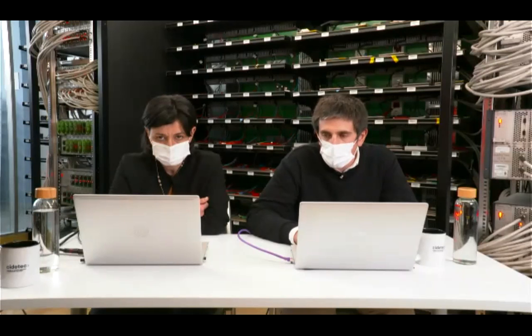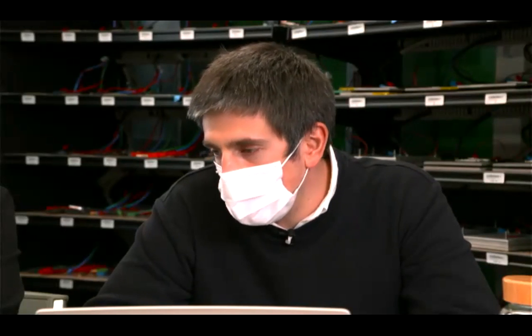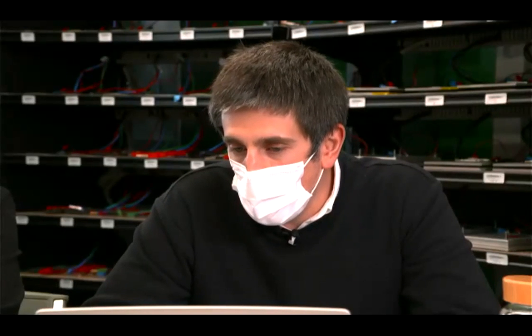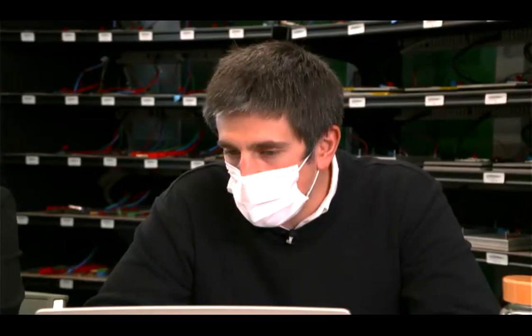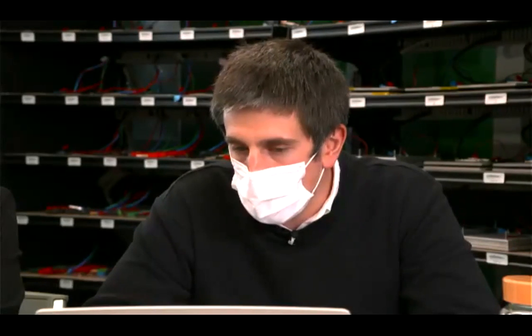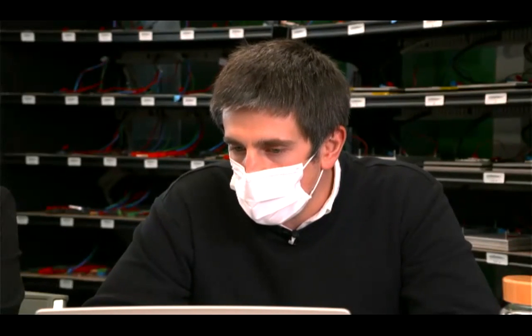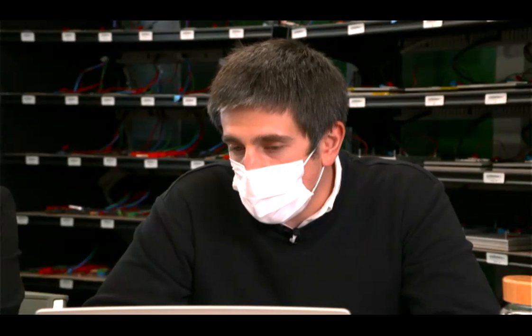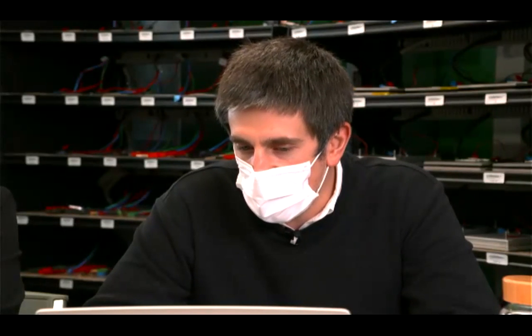So a typical temperature should be 60, 70 degrees C for the separator that we already used. However, depending on the polymer of the separator, of course, if it's more stable, maybe you can go to higher temperatures, but we have to set this with the separator type that you have in the cell.